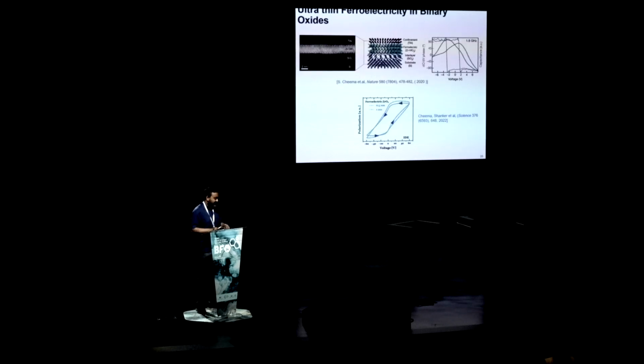And that kind of, I'm not going into the details of this work, but that kind of worked out very well. We actually saw that hafnium dioxide-based materials, even down to 1 nanometer, this TEM is for a 2 nanometer film, is actually robustly ferroelectric. So that was very interesting. And what we actually saw is that in these films, as we thin down the material, the distortion in the lattice goes up. So it becomes even a stronger ferroelectric as we thin it down.